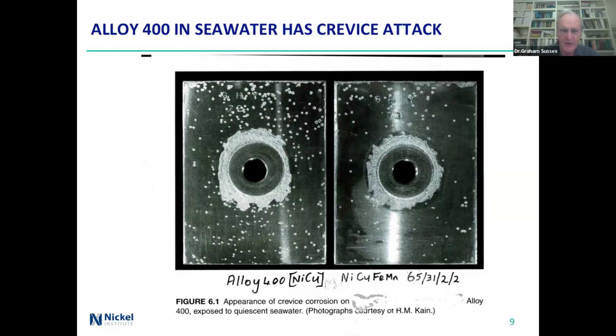This looks pretty, doesn't it? That is alloy 400, so it's very high - 65 nickel, 31 copper - so not quite so much copper, so you would expect a degree of fouling, except that that's a very, very resistant material in reducing environments, alloy 400. I was going to show a picture of this, but I didn't. Okay, so around the centre, we've got a clamp, and we've got quite a severe crevice there, and it's corroded to an extent, but it's an alloy that works in reducing environments. So it goes to 0.2, perhaps 0.5 of a millimetre, and then stops.